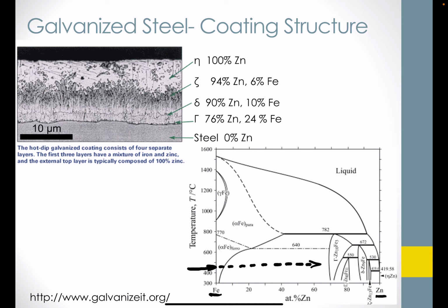And so at the outermost level, when we have pure zinc, we're at the limits here, and so that's the eta condition for pure zinc. And then as we walk to the next territory in the phase diagram, that's where we're going to see the zeta phase, which is typically about 94% zinc, and that is shown here, where there's an exact stoichiometry of zinc 13 to every iron atom. And so this is an intermetallic type situation for the mixture of the two metals in a unit